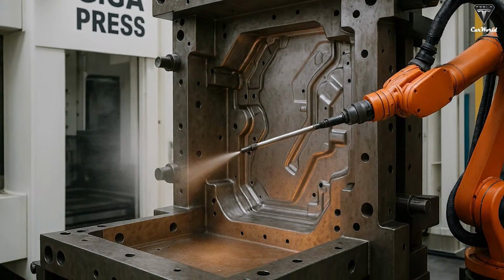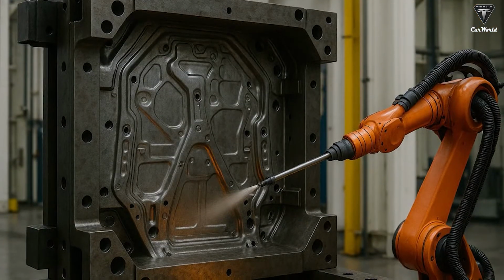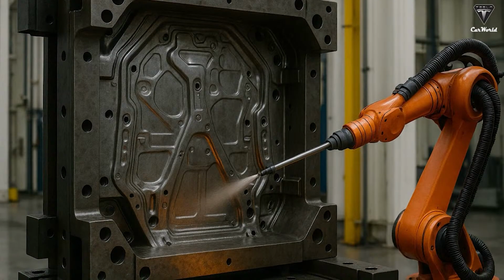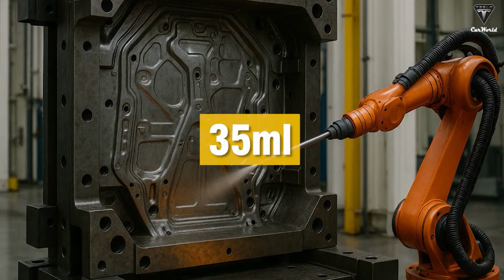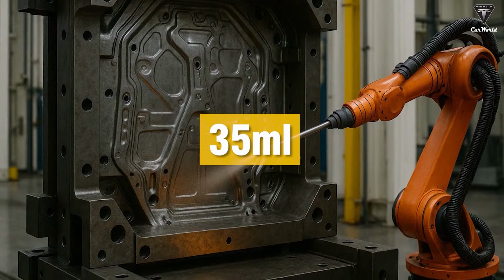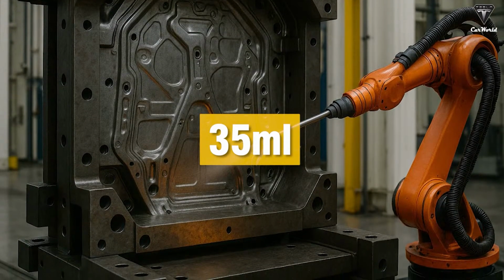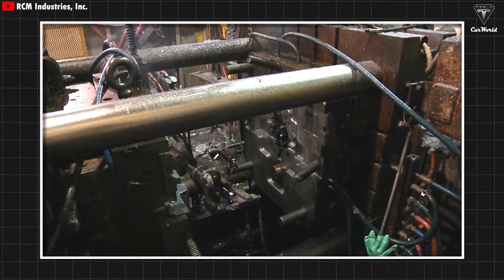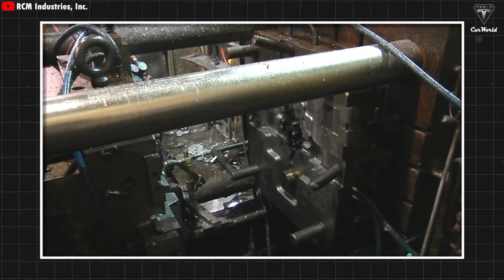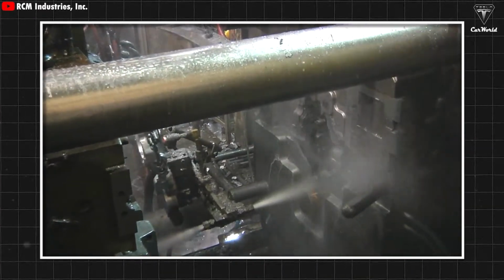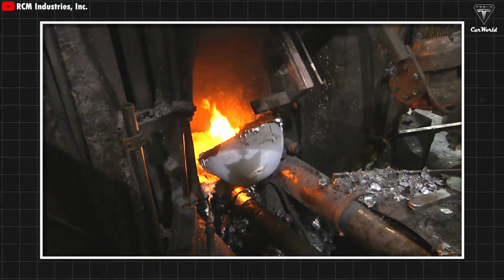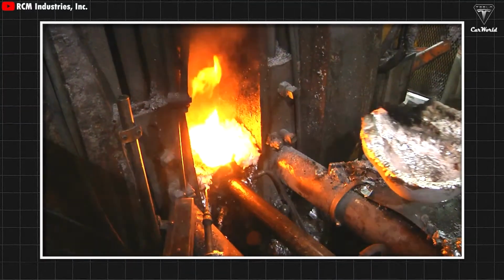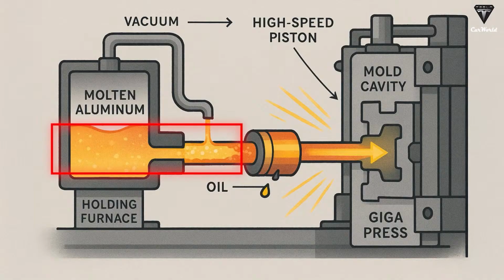Next up, mold preparation. Before each cycle begins, the Giga Press lubricates the mold surface. A robot sprays around 35 milliliters of soybean oil in a thin, even layer across the mold, kind of like greasing a baking pan, to make it easier to release the part afterward. Then the system creates a vacuum to remove any air, and the molten aluminum is transferred from the holding furnace into the Giga Press's shot chamber. There, the molten metal is injected into the mold cavity by a high-speed piston. That piston is also lubricated with about 8 milliliters of oil before each shot.